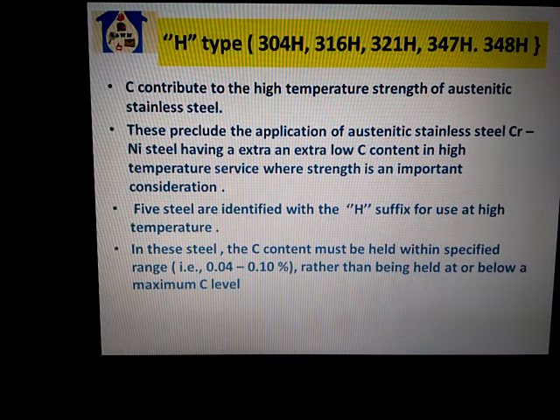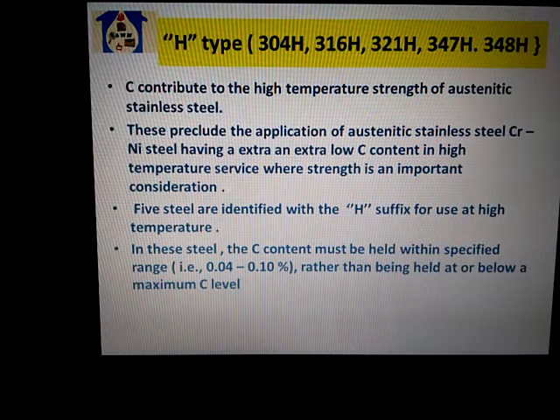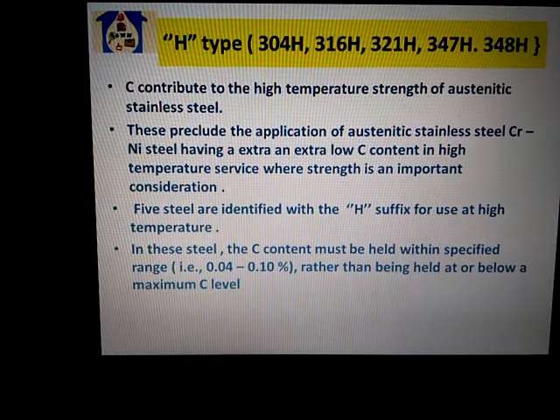H types 304H, 316H, 321H, 347H and 348H contribute to the high temperature strength of austenitic stainless steel. This precludes the application of austenitic chromium-nickel steels having extra low carbon content in high temperature service, where strength is an important consideration. These steels are identified with an H suffix for use at high temperature. In these steels, the carbon content must be held within a specified range, like 0.04 to 0.10%, rather than being held at below a maximum carbon level.